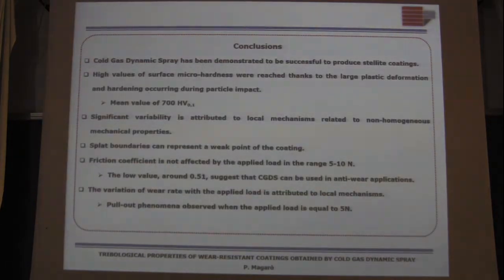In conclusion, cold gas dynamic spray has been demonstrated to be successful to produce stellite coatings, and the high values of surface microhardness were reached thanks to the large plastic deformation and hardening occurring during the particle impact. In particular, a mean value of the microhardness equal to 700 Vickers was obtained. But a significant variability is attributed to the local mechanism related to the non-homogeneous mechanical properties. In fact, the splat boundaries can represent a weak point of the coating.